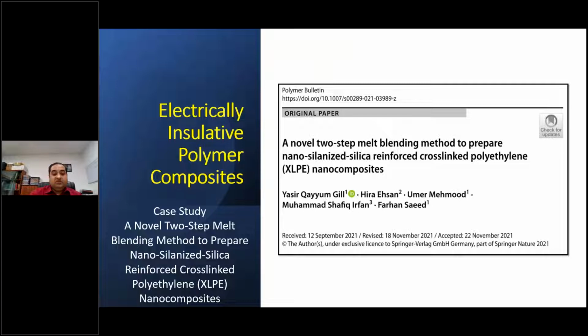The ratios and the SEM surfaces, which show no presence of any agglomerate formation, are shown to you in this slide. The thermal properties, the densities, the breakdown strength, the solvent uptake, and the flammability showed that with the inclusion of silica, we were able to develop electrically insulated products with enhanced properties. And a slide over here shows you the overall data in terms of the gel percentage, the solvent uptake, the density, and the breakdown strength.